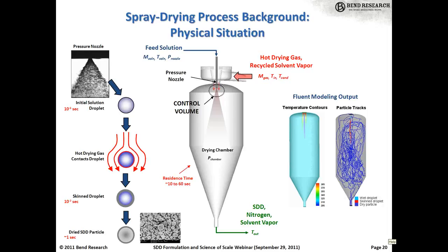That feed solution gets pumped through an atomizer where it gets broken up into droplets that are contacted with hot drying gas. We typically use nitrogen as the drying gas because we're working with flammable solvents. So almost immediately after the droplets are contacted by the hot drying gas, solvent begins to evaporate, and the droplets begin to evaporatively cool such that they're at their wet bulb temperature and will remain at or below the outlet temperature of the spray dryer through the entire drying process. So the spray drying process can be relatively mild temperature-wise, so it's suitable for APIs that may be heat or temperature sensitive.